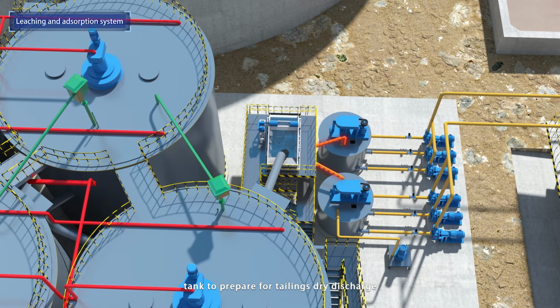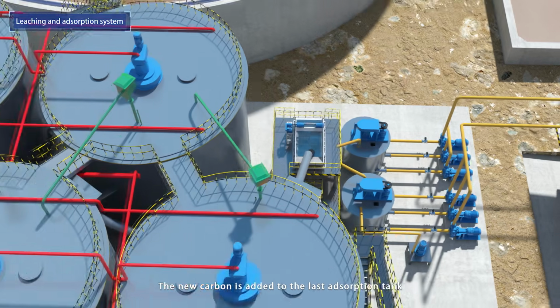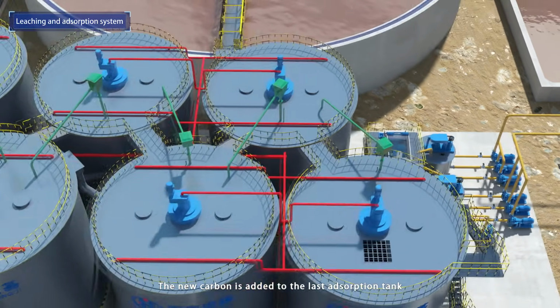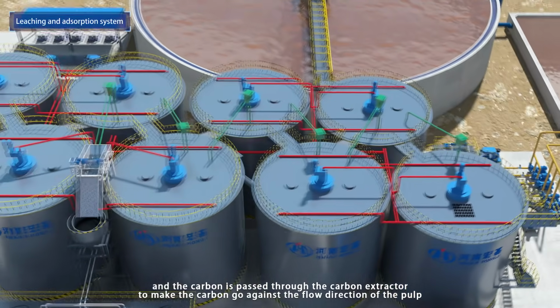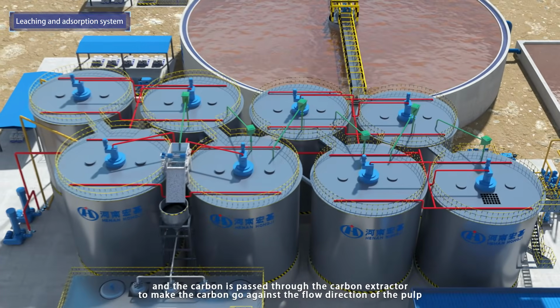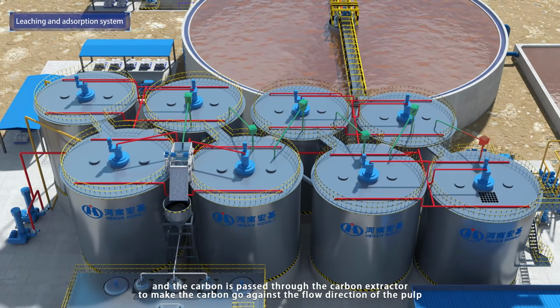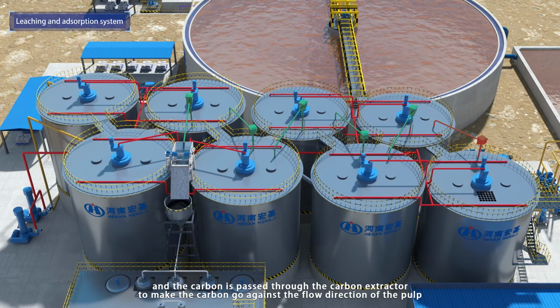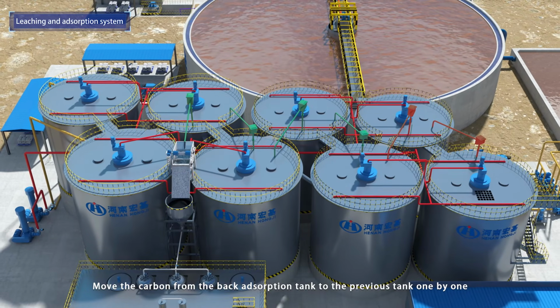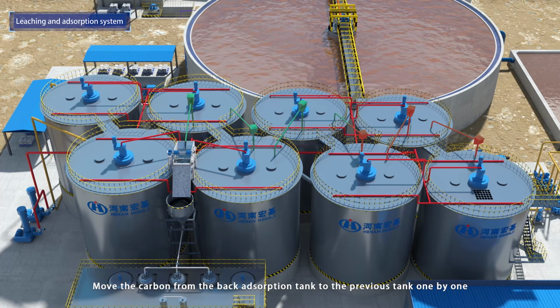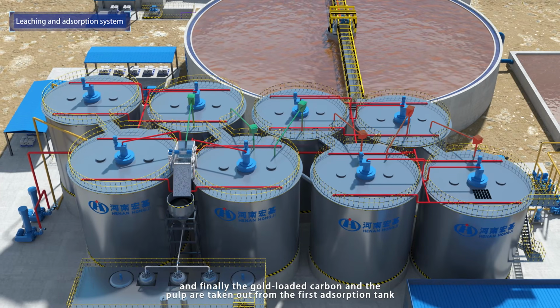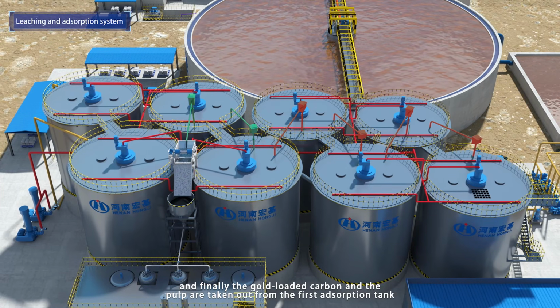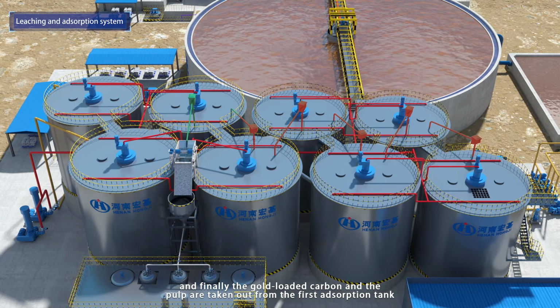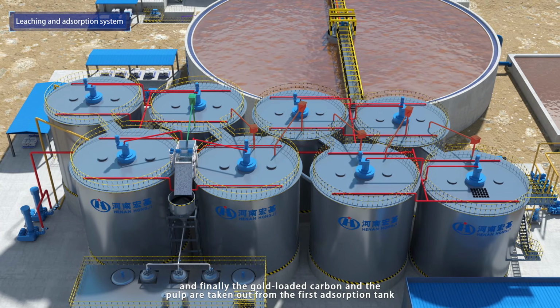tailings dry discharge. The new carbon is added to the last adsorption tank, and the carbon is passed through the carbon extractor to make the carbon go against the flow direction of the pulp. Move the carbon from the back adsorption tank to the previous tank one by one, and finally the gold-loaded carbon and the pulp are taken out from the first adsorption tank.